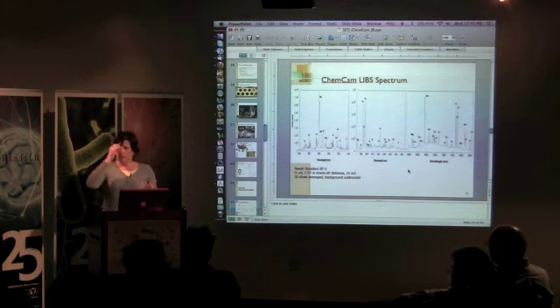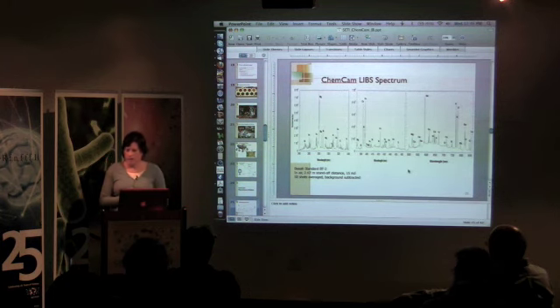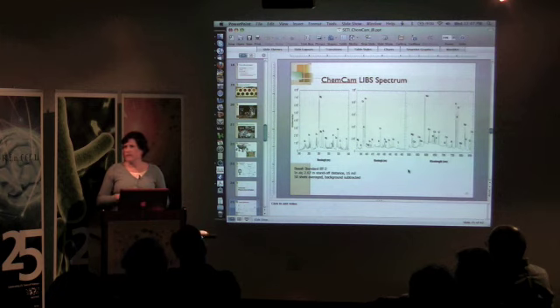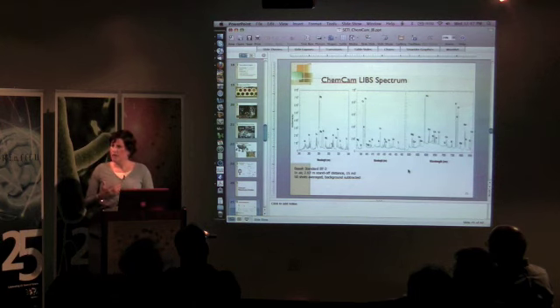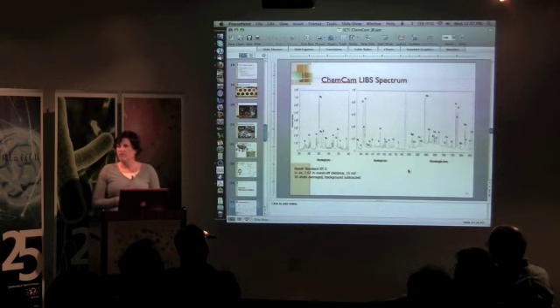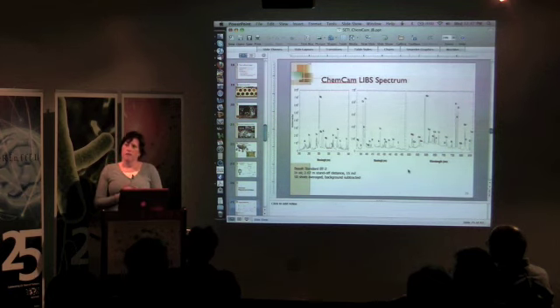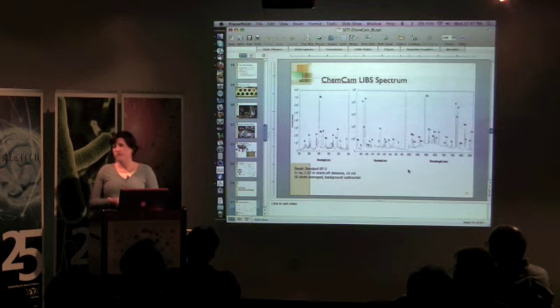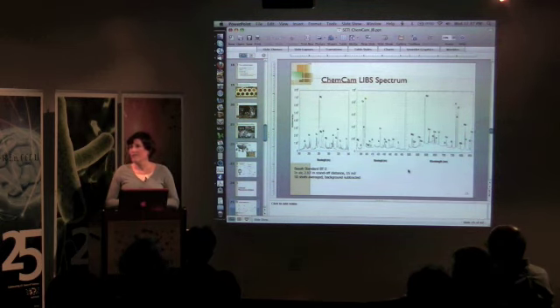Is that your question? In terms of the carbon suite, I showed data for carbonates, but one of the thrusts of Anna Lilla's PhD thesis work is to try to determine what the detection limits are for organic carbon in rocks in a Martian atmosphere. To that end, we've used stream sediments, lake sediments, shales, and because all of those are variables that determine how well the laser couples with your target material, we have a lot of variables there. It's interesting because we're seeing much higher carbon lines in, say, a shale sample that has 3 weight % organic carbon determined by other methods, compared to a set of Canadian stream standards that have up to 12 weight % organic carbon. So there are a lot of complexities we're still trying to explore.